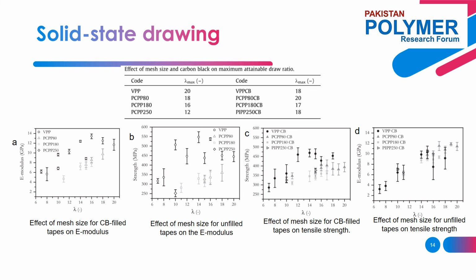The effect of melt filter mesh size on the mechanical properties is shown in figure A, B, C and D. For both unfilled and carbon black filled material, the elastic modulus and tensile strength are not directly affected by the size of the mesh, but they can be drawn further, yielding drawn tapes with enhanced properties. The maximum tensile strength of 385 megapascal was obtained for post-consumer filled polypropylene with 80 mesh filter at 18 draw ratio, which is an improvement of 15 times compared to the isotropic tensile strength of 20 megapascal.